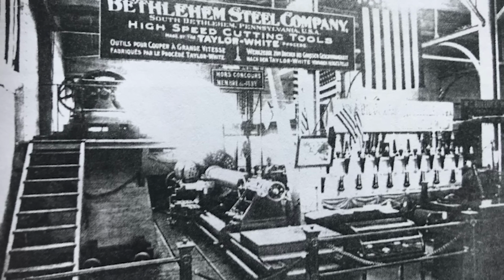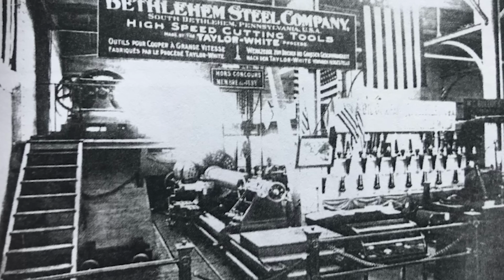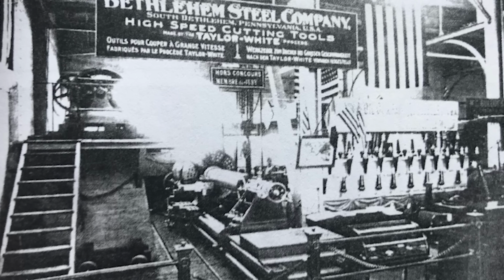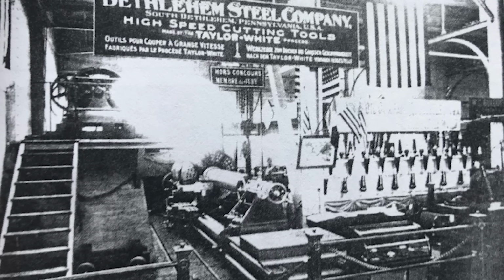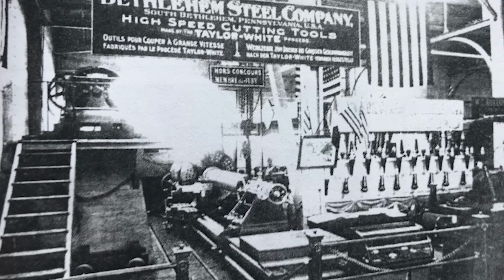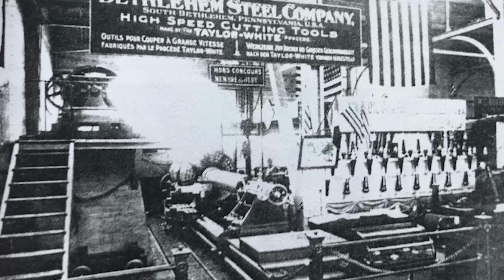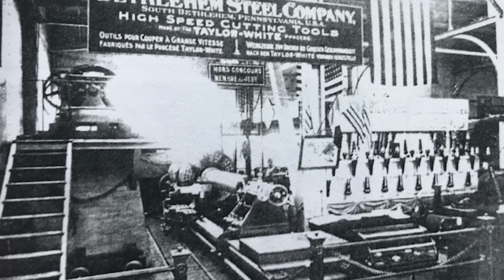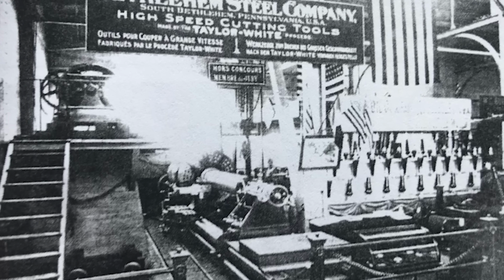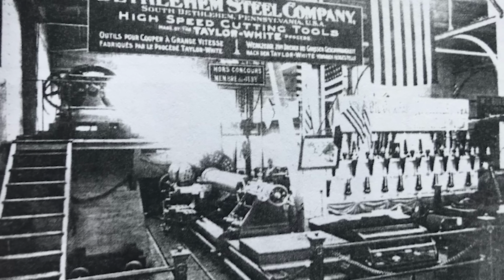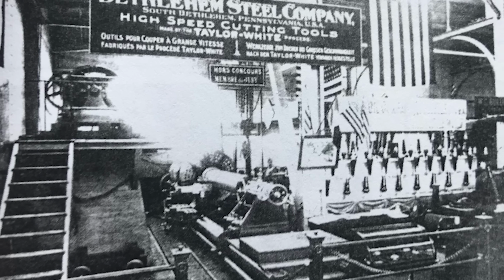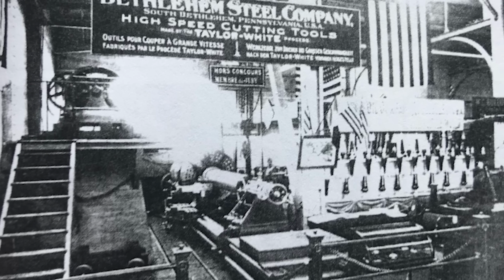For 3 decades, every machine shop from Pittsburgh to Chicago had accepted the same brutal mathematics: 30 surface feet per minute maximum cutting speed, or watch your tools lose their temper and go soft. European experts had proven this limitation was absolute, unbreakable, yet Taylor was heating his experimental steel to 2100 degrees, red-hot temperatures that should have destroyed the metal's structure completely.